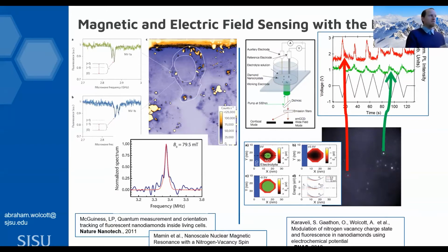Now, if you were to read this paper in depth, what you would see is that the absolute number of particles that actually blink, that respond to the voltage, was only about 20%, 25%. And the issue here is that most of the NV diamond was stable in its fluorescence and didn't respond to the voltage. And so that really got my mind going that, well, perhaps the surface structure of the NV diamond has not been destabilized enough to allow for that charge switching to readily occur.